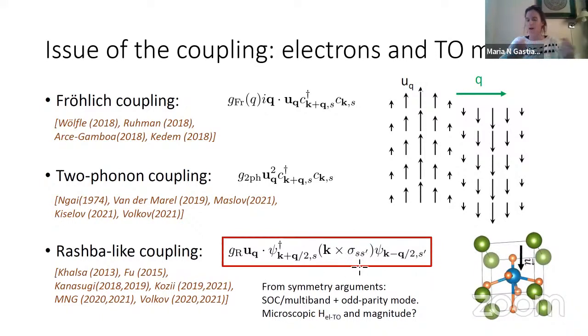Here I'm connecting this U to the spin of the electrons. This is a non-magnetic displacement that is somehow talking to the spin. And how can that be? That is because I have to allow for spin-orbit coupling. It was pointed out a few years ago that if you allow for spin-orbit coupling, you can get a Rashba-like coupling between the electrons and basically anything that breaks inversion. And then what I'll do next is show, from a microscopic point of view, how this kind of coupling arises in these systems.